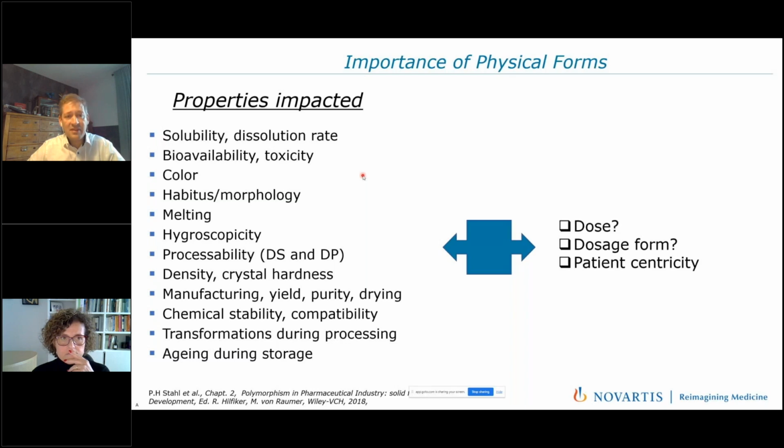This will certainly impact the processability of the drug substance in terms of filterability and drying, but also the drug product manufacturing. They will also have different melting point, different hygroscopicity, meaning how sensitive the drug is depending on the exposure to relative humidity. And certainly, ultimately, a very important parameter is the chemical stability and the compatibility with the excipients.